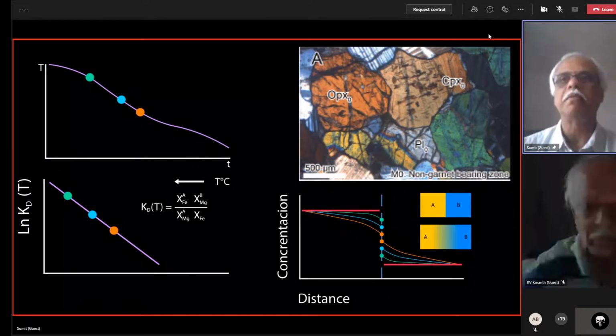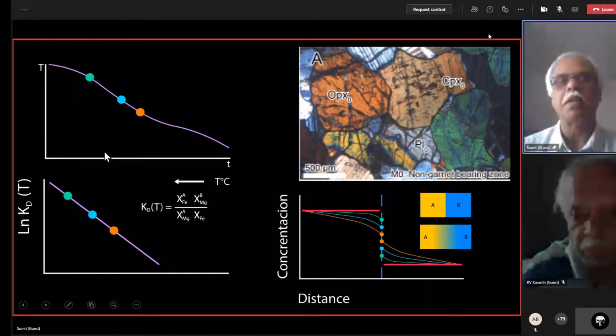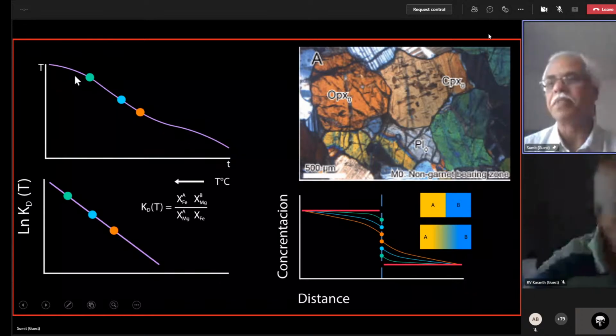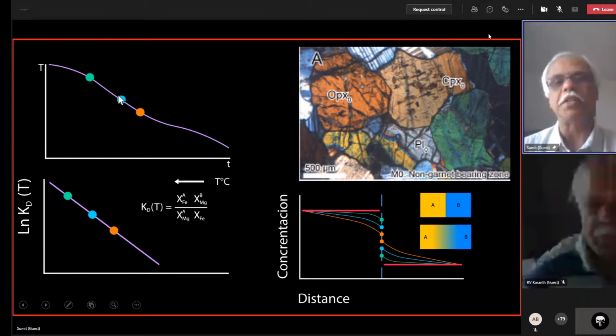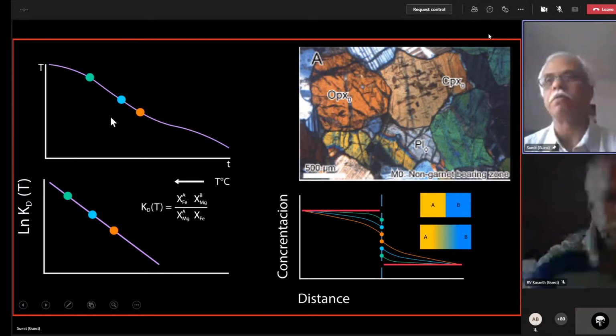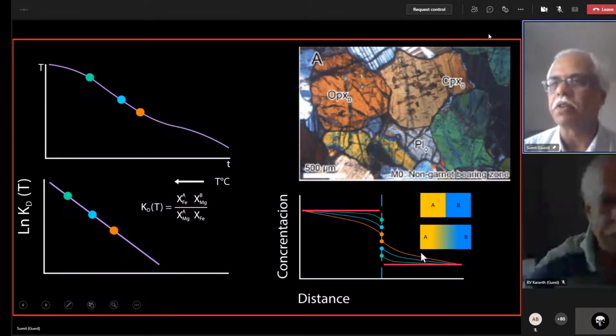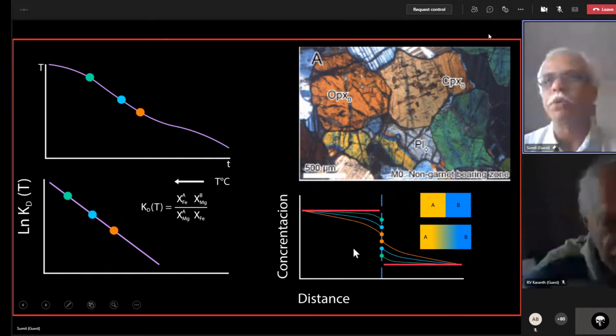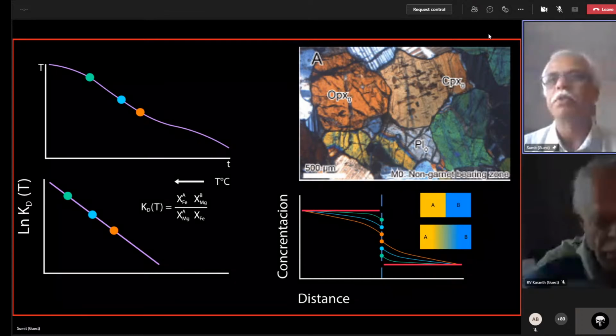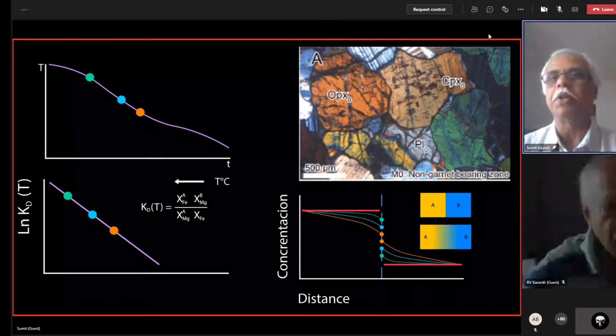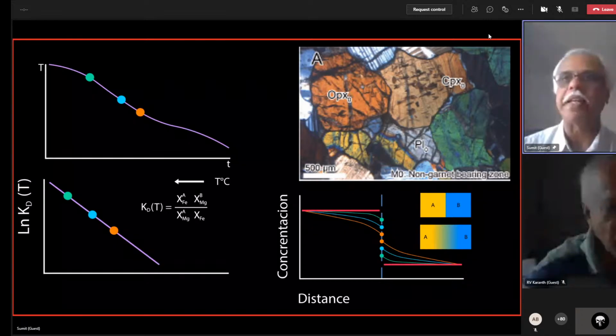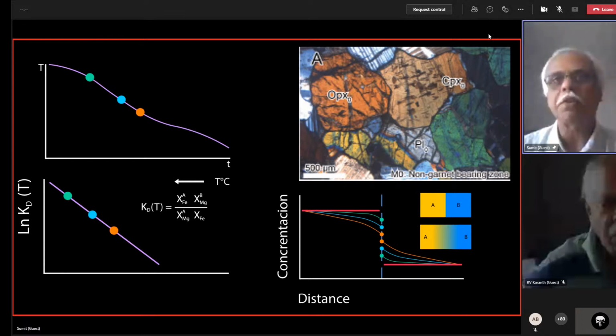If I cool the same thing very slowly, so I go through the same temperature, but at different times. So the gap between the red and the green is now, let's say, instead of 1 million years, 10 million years. And from green to blue, you have another 10 million years. And from blue to orange, you have another 10 million years. So the whole thing is, let's say, 40 million years. Then obviously, these atoms here have much more time to diffuse, and the concentration profile that you measure will be completely different. So that now gives you a tool to not only measure the pressure and temperature that the rocks have seen, but also how quickly the temperatures changed. So do we see that in real rocks? We do.